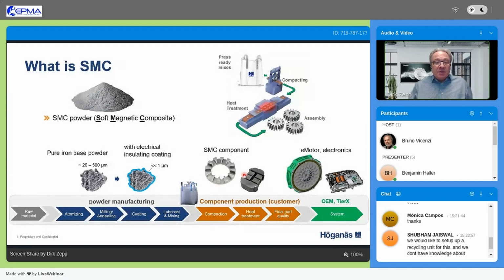The material itself, SMC, stands for soft magnetic composite, and it is manufactured by creating a pure iron-based powder material with no other ingredients, just the pure iron, then a very specific coating around each particle as an insulation, with a very small thickness of just a few micrometers. This is what we produce in our facilities, the base material in Sweden, which is quite important. We come to that later on in the LCA phase. Then we sell this in big packs to our direct customers, the compaction companies, which produce the final products with compaction tools and heat treatment. And then, of course, the end customer assembles it and uses it for the final application.